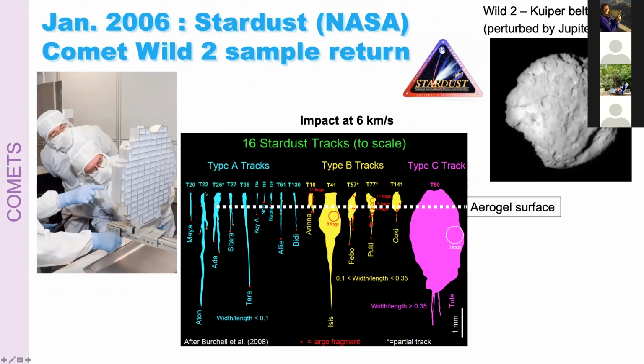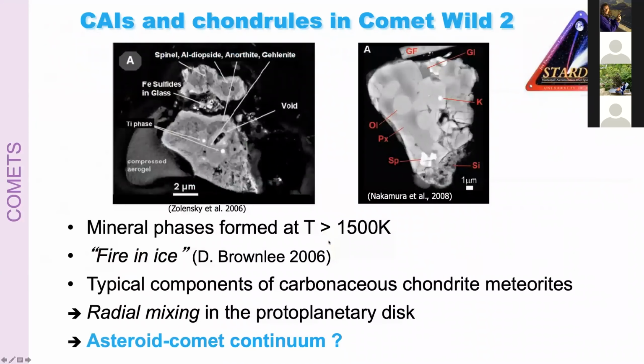And so what happened is that since the aerogel is very thermally insulating, the samples exploded in the aerogel, and then mostly only the coarse grain minerals survived as the red dots here at the end of the tracks. But it already gave a lot of information, namely the fact that there were high temperature mineral phases in these samples, like a refractory inclusion, like the one you see here, and a fragment of chondrule. So these are both phases that are very typically found in carbonaceous chondrites.